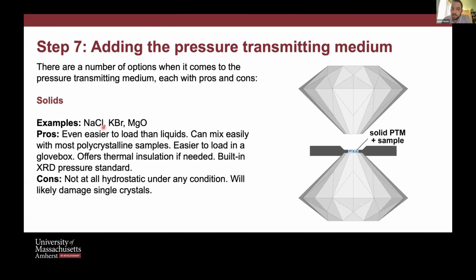You know, if you have the equation of state, you don't need to know precisely, because it's certainly less accurate than other methods, but if you just need to know roughly what GPa you're at for preliminary measurements, you can just use the X-ray lattice parameters of the pressure medium itself. But the downside is that it's not really hydrostatic under any condition. I'll correct that because I noticed Stas said that it's not so bad at low pressures. So maybe sodium chloride is okay if you're at pretty low pressures, but just like the liquids, beyond a certain point, it's not going to be hydrostatic. And you're probably not going to maintain your single crystal.